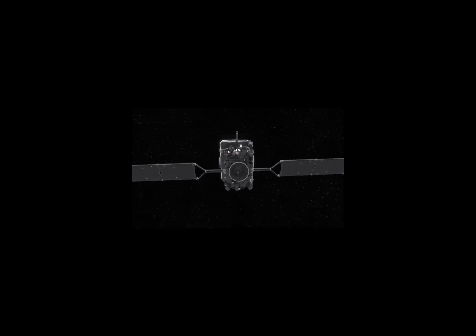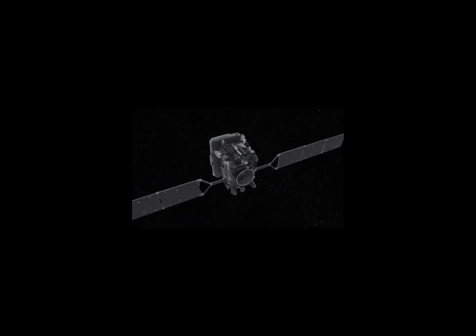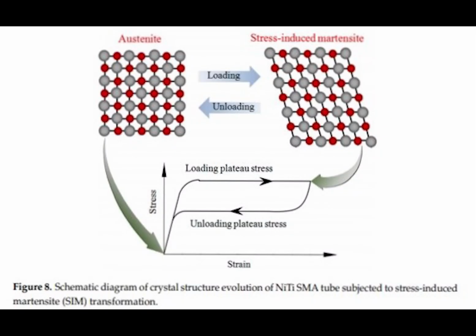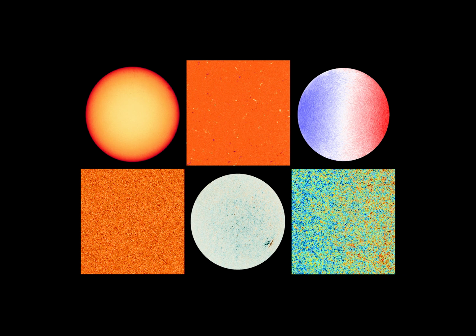There are several SMAs that could perform the martensitic transformation required. Nickel titanium alloys, which are often used in satellites, boast a melting temperature of 1310 degrees C and have a transformation temperature of approximately 100 degrees C, making them well suited to activate in solar orbit. Each part of the solar orbiter demonstrates the importance of careful material selection and consideration during the design stages. If there were even one inaccuracy in the properties of the materials used in the orbiter, the project would face an expensive failure. In July, the first images were published of the spacecraft halfway between the Sun and the Earth.